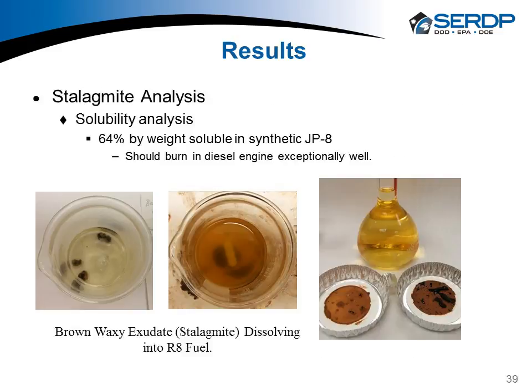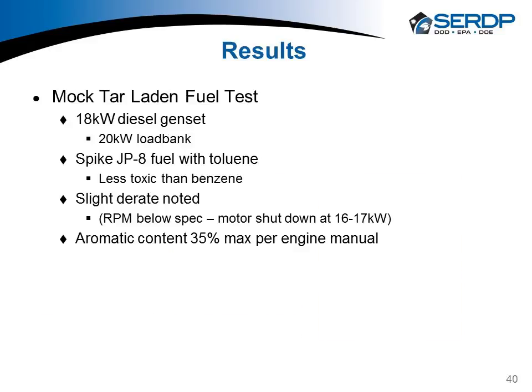This waxy material was soluble in the synthetic JP8. You can see it going into solution here with a little bit of heating. When we filter it, we find it's 64% by weight soluble in the JP8. And I think if you look at the burning of straight chain alkanes, it would probably burn just fine in diesel fuel. Even though it's a longer molecule, I think it would unzip pretty fast in the combustion chamber and give you energy.